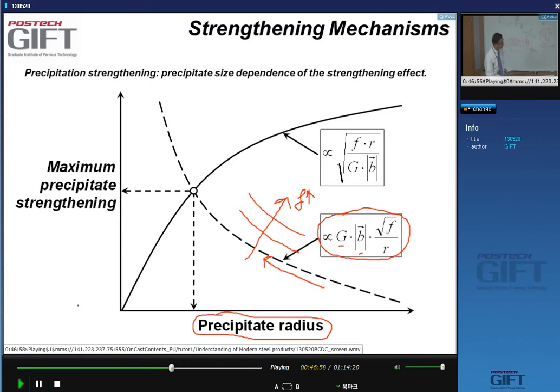And it's very different from the case where you have a particle shearing. There, this r, the radius of the particle, is not in the denominator, but the strengthening is proportional to the square root of f times r. So in this case, the strength increases with particle size. But as I said, in steels, this is the kind of strengthening that we are dealing with.